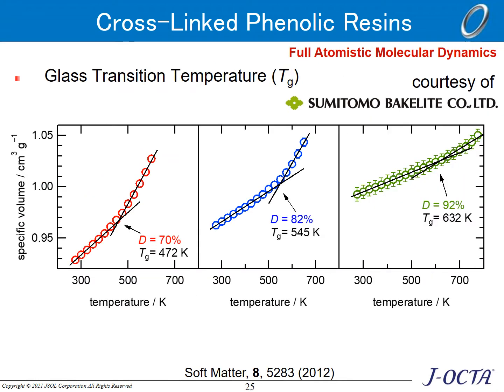The temperature is gradually lowered, for the structure obtained from the reaction calculations. These graphs show the specific volume at each temperature. The red, blue, and green graphs show the results for the cross-linking ratio at 70%, 82% and 92%, respectively. The slope of the graph represents the thermal expansion coefficient, and the point at which the slope changes is the glass transition temperature.